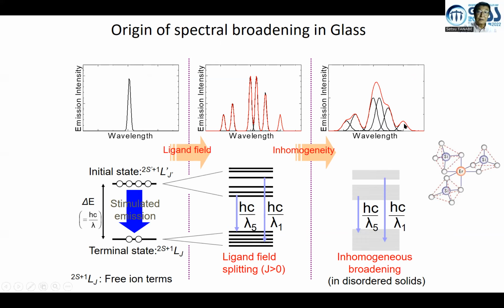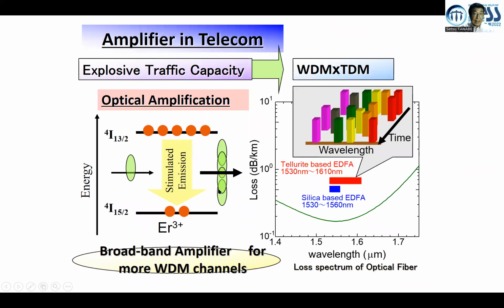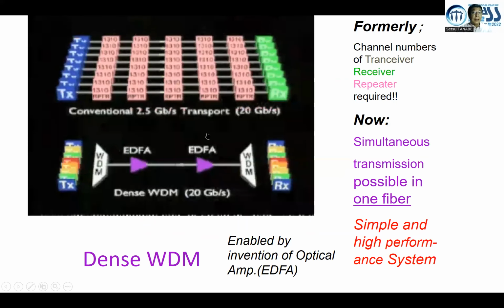with non-zero J Stark splitting gives this complex splitting spectrum. EDFA is made of silica-based glass, or sometimes tellurite or fluoride, having different characteristics. Parallel amplification is possible, and combined with time division multiplexing, high-capacity telecommunication is achieved. This is a comparison of old-fashioned telecommunication and WDM telecommunication after the invention of EDFA. By WDM, 8 different channels are coupled into one fiber, and because of the large gain of the amplifier, the number of intermediate repeaters can be decreased. So the system becomes much more simplified by the development of the erbium-doped fiber amplifier, and dense WDM becomes possible.